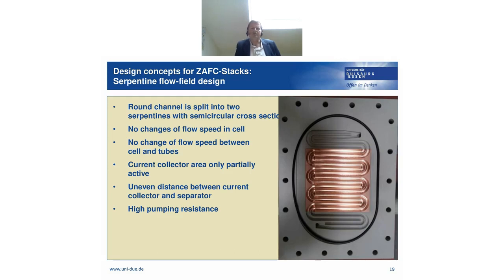We also developed other flow field designs here for the anode. It's a serpentine flow field, and the zinc slurry enters through a round channel at the bottom, and then is split into 2 serpentines with semicircular cross section, and then it exits at the top right again through a round channel. So there are no changes of flow speed between the cell and the inlet and outlet tubes. And we see the current collector, which is made of copper. There are 2 disadvantages of this serpentine design. We have an uneven distance between the current collector and the separator, which lies just above this flow field. And because of the serpentine structure, we have a relatively high pumping resistance.